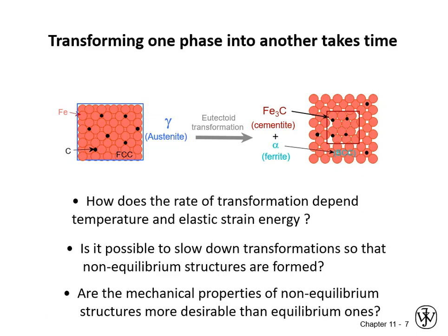So if we imagine a eutectoid microstructure or proeutectoid up in the austenitic range, we're probably in the range of less than 1% carbon on an atomic scale. So fewer than 1 in 100 atoms in the lattice are going to be carbon. So carbon's pretty spaced out.